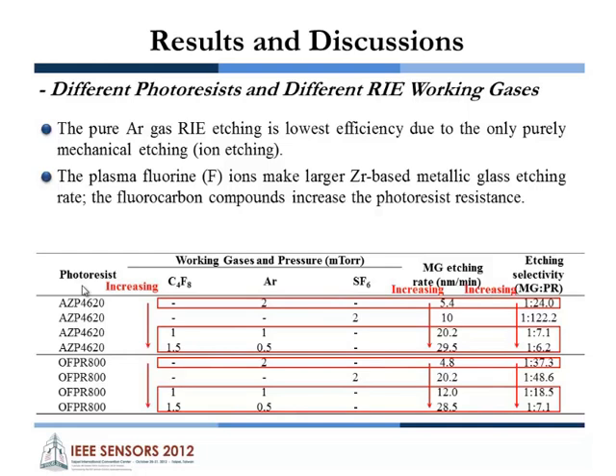Looking at C4F8 and pure argon here, when we increase the C4F8 ratio, the etching rate increases. This is because C4F8 has plasma fluorine ions that can do chemical etching, but argon only has mechanical etching. But we can see the etching selectivity also increases, because the fluorine carbon compounds from the C4F8 can increase the photoresist resistance.